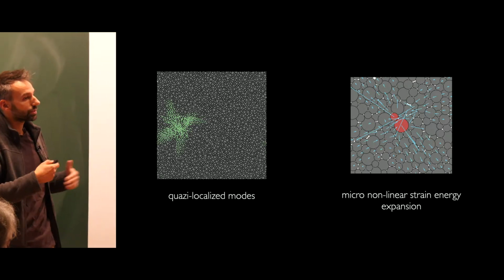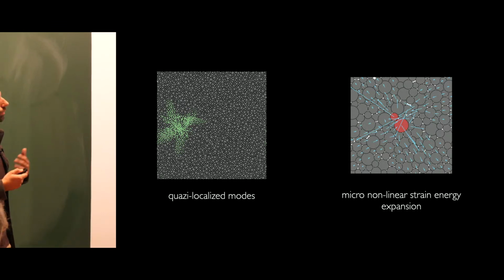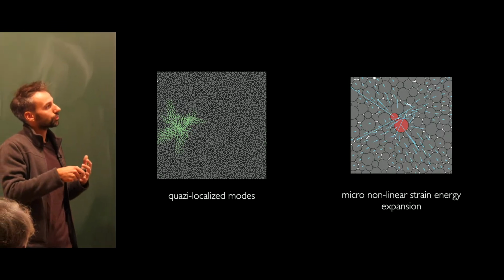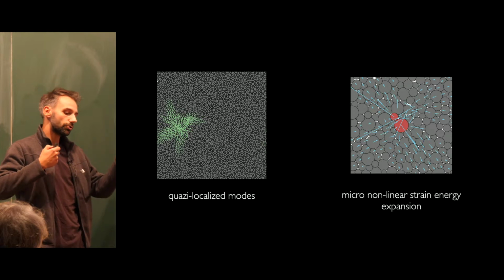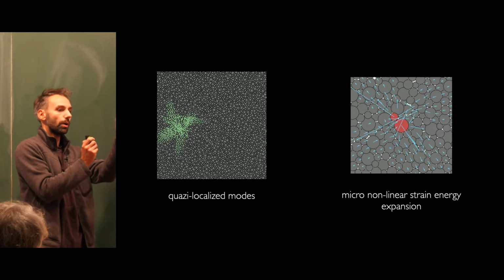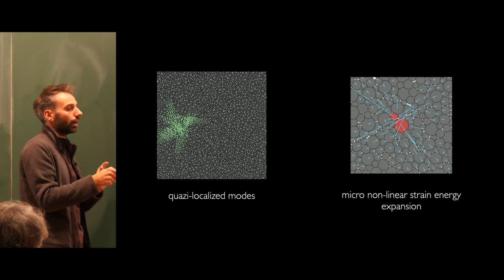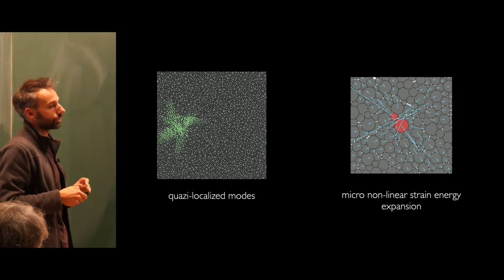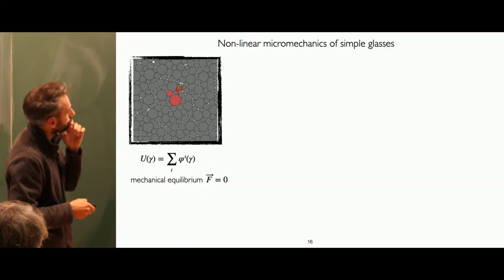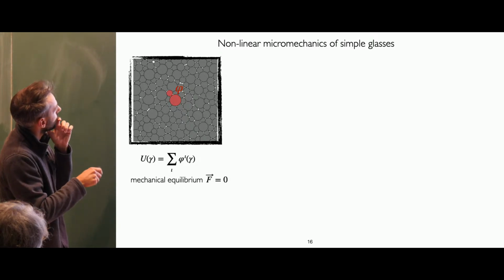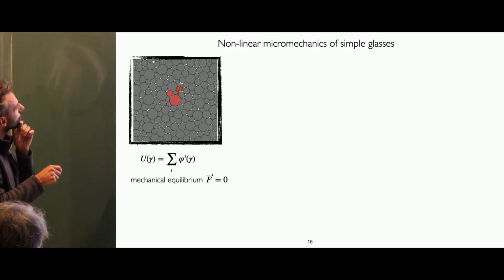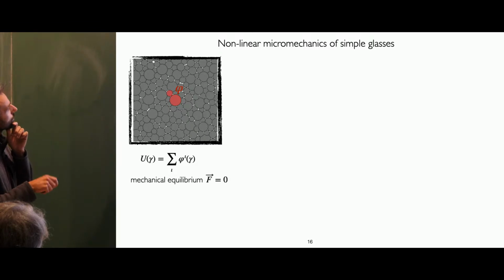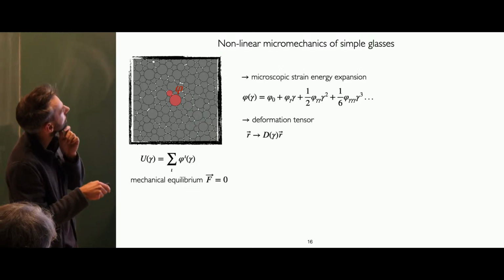And one step that we did before reaching this point was to try to understand already, if I had a pairwise energy, what is the micro nonlinear strain energy expansion associated with this? So what is the strain dynamics of a pairwise energy in my system, and how is it related to quasi-localized modes? So I'm considering a glass with a pairwise energy between 2 particles. The energy of the system is just the sum of all the energies, and my system is force balanced.